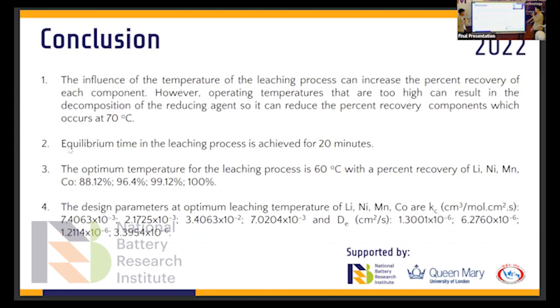So the conclusion of our research: first, the effect of temperature and time has a positive correlation on percent recovery, and we get the equilibrium time of the leaching process is 20 minutes and the optimum temperature is 60 degrees Celsius, and the design parameters at optimum leaching are the following.